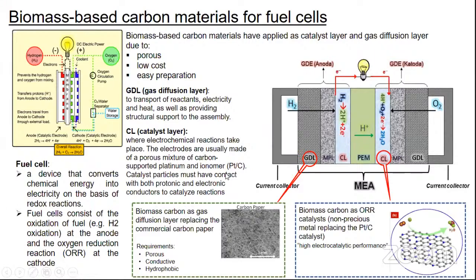Biomass carbon has the potential to be utilized as a gas diffusion layer, replacing the commercial carbon paper, due to its porous and conductive nature. In order to perform the GDL function, a GDL should have appropriate porosity, good electrical conductivity, proper wetting characteristics, and enough strength. They are the primary requirements that must be possessed by a material to be applied as the GDL of a fuel cell.